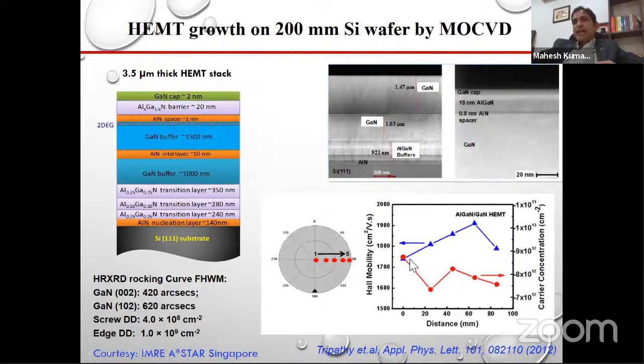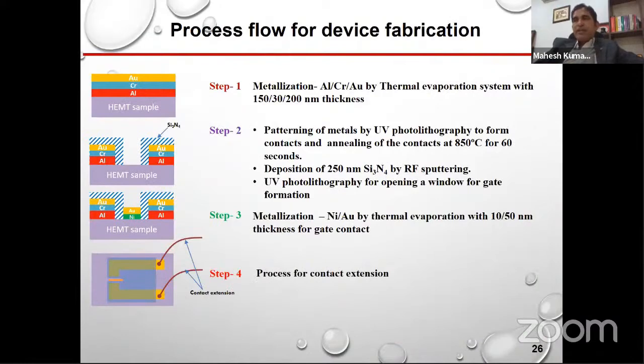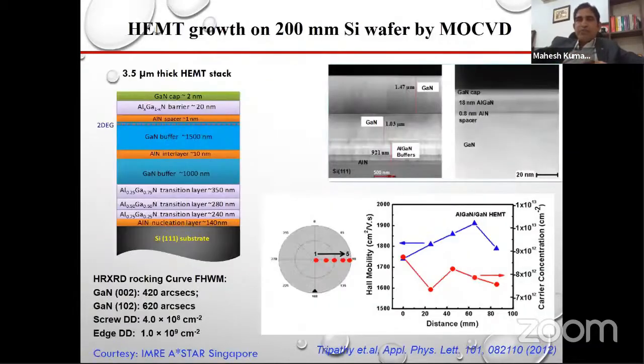Regarding mobility at the heterojunction: in gallium nitride mobility is low, in aluminum gallium nitride mobility is low, but at the heterojunction mobility is high, around 1700 centimeter square per volt per second. Then at IIT Jodhpur, we have deposited the contacts. We have deposited aluminum, chromium, and gold, because for source and drain contacts we need minimum contact resistance. If you deposit gold directly, you see one more thing, because this 2D electron gas is forming here.